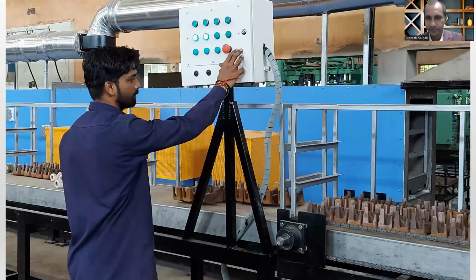Yeah. Okay. Next question is related to, if sometimes our sand comes in, particularly in the rainy season, in a moist condition, and it is very difficult to dry it. Normally it is expected that 0.1 should be the moisture of the silica sand to be used for the core, but 0.2, 0.3 also somebody is using, and they are not using any paint. So in that case, whether unpainted core can be passed through this oven to reduce the moisture content that core has? Absolutely. You can pass it through this to reduce the moisture. So that moisture will be reduced. Yes.